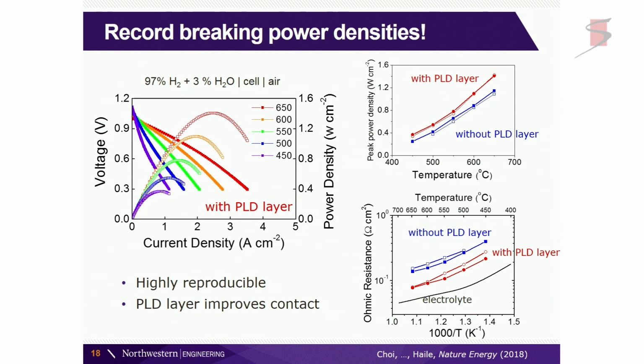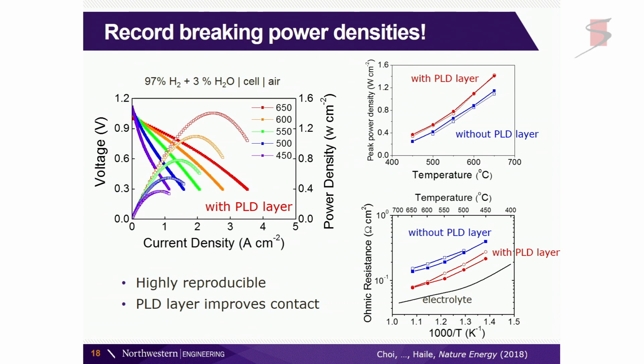I'll put this in the context of the prior literature in a moment, but we're drawing amps per centimeter squared here, just to put this in the context of some of the other numbers that you've heard. And this is at now moderate temperatures, so we're not at 800, 1,000 degrees Celsius, which is the case for the oxygen ion conducting systems.